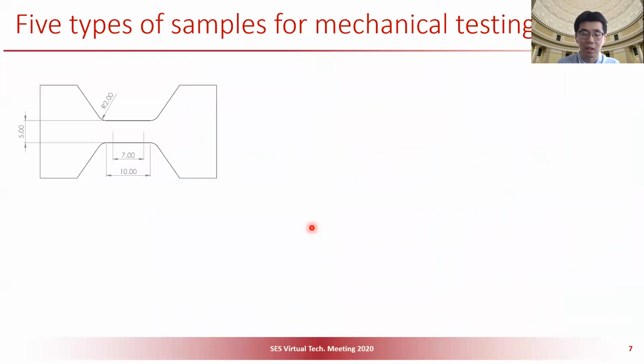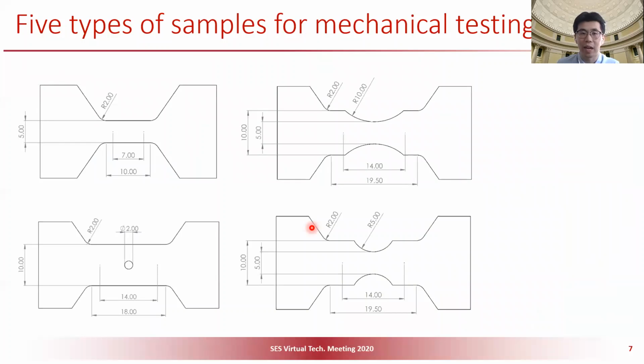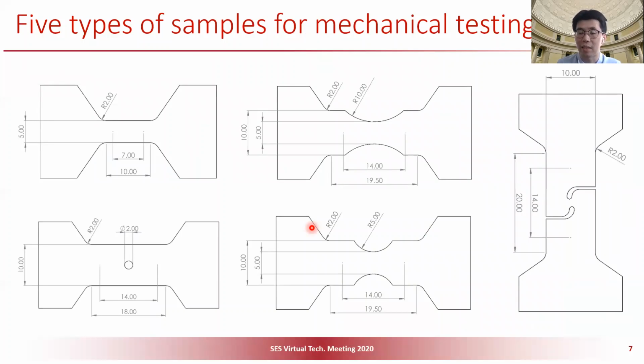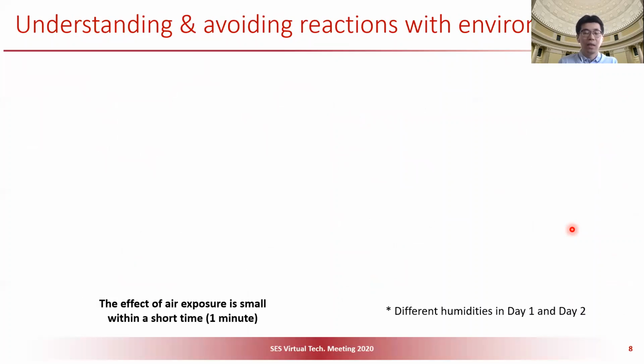With this cutting technology, we designed 5 different types of mechanical test samples. So this is uniaxial tension, central hole tension, notch tension with a very smooth notch, and sharp notch tension. And this is probably the most complicated one. This is a simple shear test. As you can see, this sample has a very, very complex geometry. So that's the advantage of laser cutting.